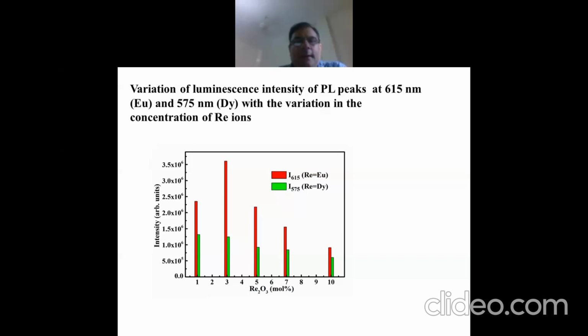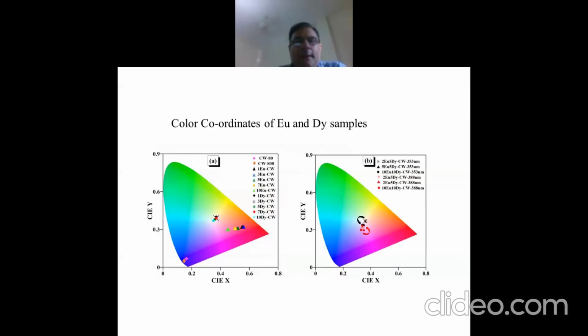oxide doping, the intensity of photoluminescence yield decreases continuously. So much stronger quenching effects are visible in dysprosium oxide doped materials, and dysprosium emits green light, which is centered at 575 nanometers, and europium emits strongly in the red part of the visible electromagnetic spectrum.